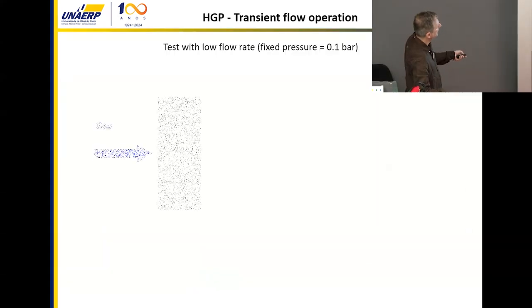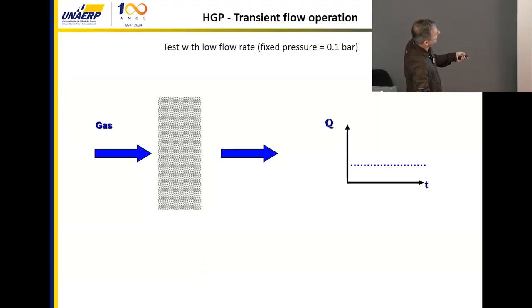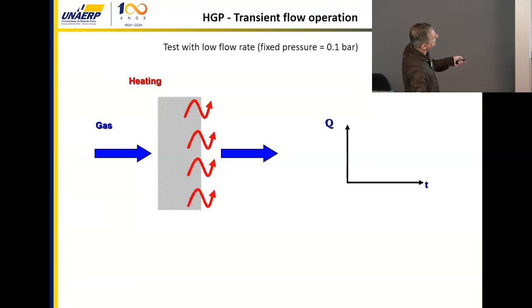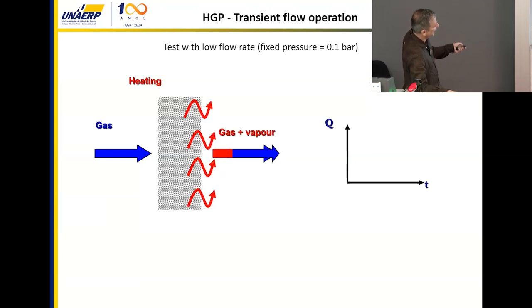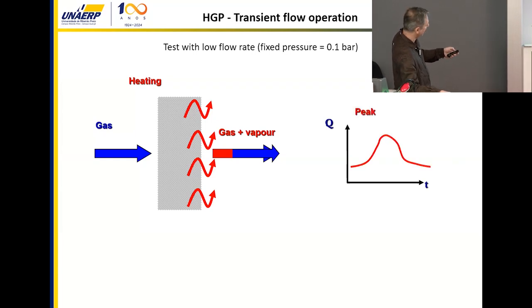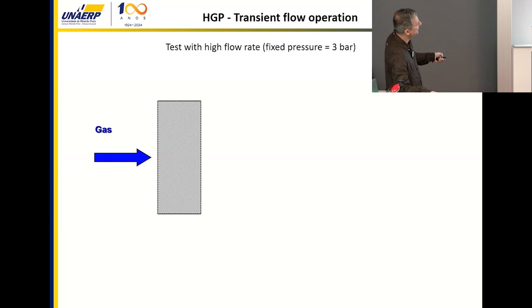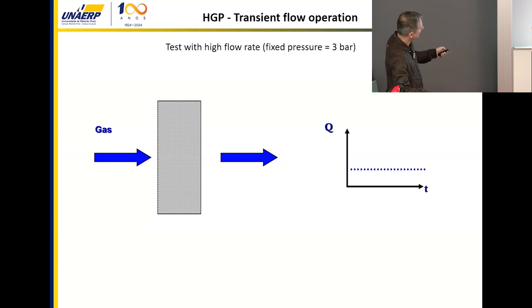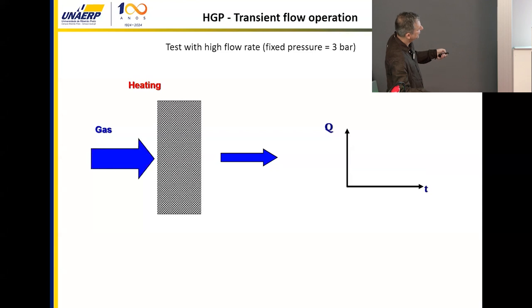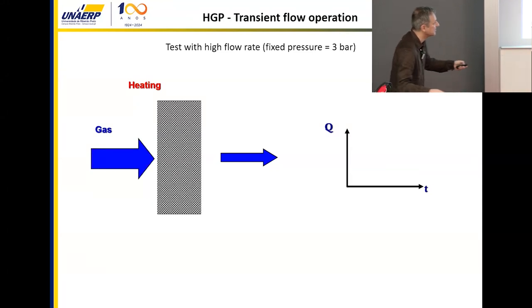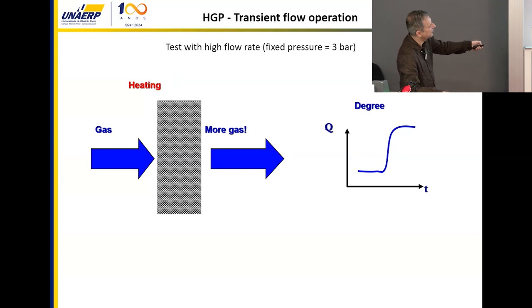This is the material. This is to show that as we heat the material, you get the signal of, for example, vapor. And if you have the vapor, you have the peak, and we can track the peak of the gas flowing through the material. This is another test with a high flow. If you have the same temperature, you have the flow always constant. But as you heat, you can have more flow because the structure opens, and you have a degree signal or a peak signal.